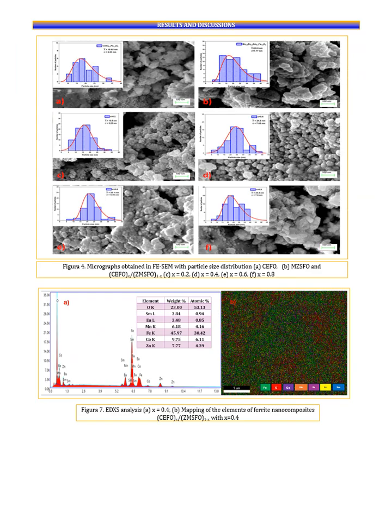The results analysis also shows the field emission scanning electron microscopy, FESEM, micrographs of the nanocomposites. The images revealed that the morphology of the synthesized samples consisted of agglomerated grains with spherical shapes. The agglomeration in the micrographs may be due to the magnetic properties of the ferrite. The particle size distribution was also determined from the FESEM micrographs using ImageJ software, which provides average particle sizes of 21.5 nanometers. In addition, EDXS analysis and elemental mapping of the nanocomposites were performed and are presented in Figure 7.